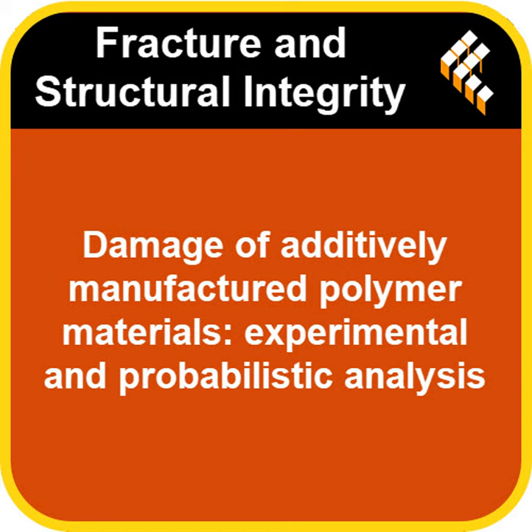This indicated that applying that thin layer of white color, which they did via colored printing in that layer, had minimal to no measurable effect on the key mechanical properties like tensile strength, yield strength, or how much it stretched before breaking, the elongation, at least not under tensile stress in this study. Okay, so the coloring process itself didn't seem to weaken the bulk material significantly. That's good to know, I suppose, if you're planning to paint your printed parts, although here it was for a technical measurement reason. Right. It implies that, at least with this specific method and under these tensile conditions, that surface treatment wasn't detrimental to the structural performance. It didn't compromise the bulk strength.